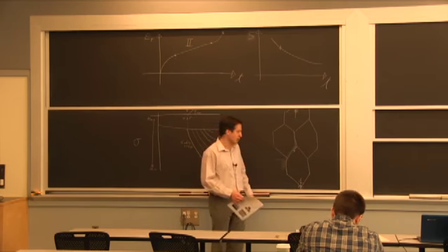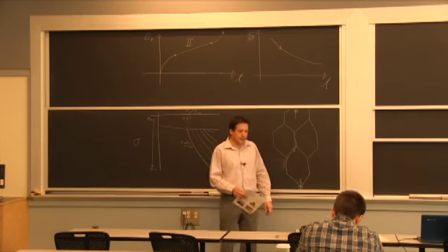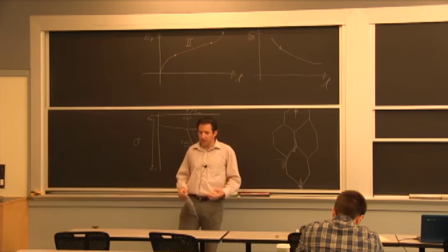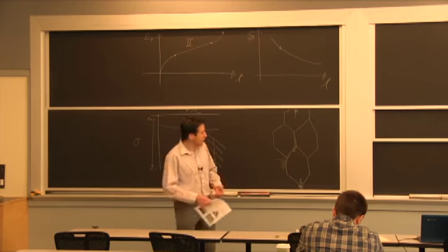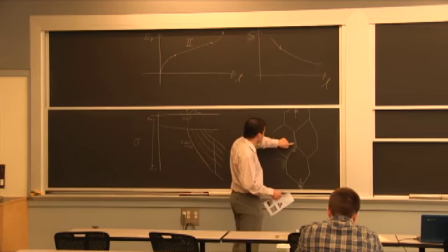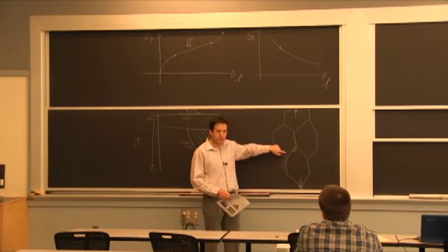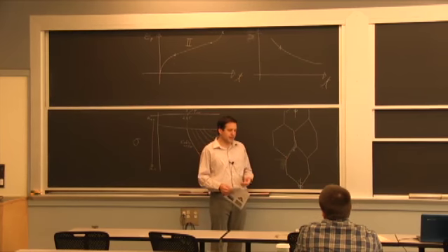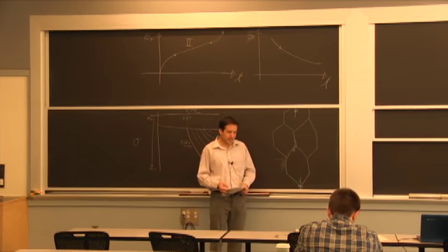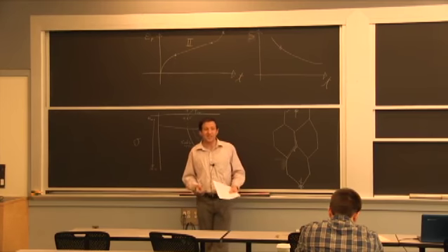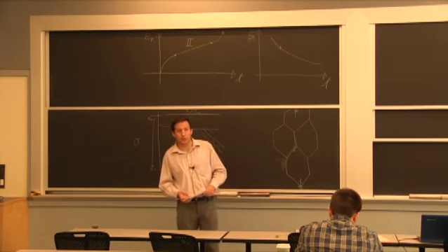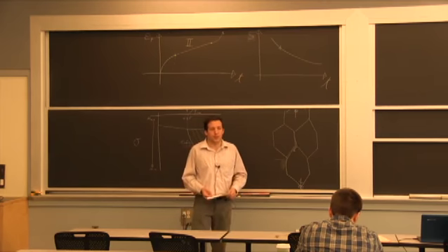because of the tension. Now, I say there's little vibration, meaning that it'd be really hard for these atoms to diffuse through the grain, because the grain essentially is very solid, doesn't have too many vacancies. You need vacancies for diffusion. These are just holes in the crystal.